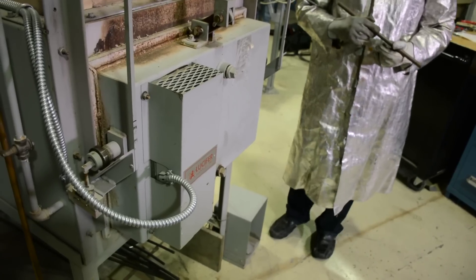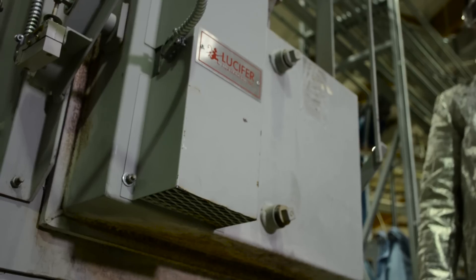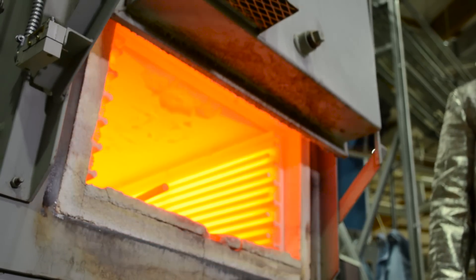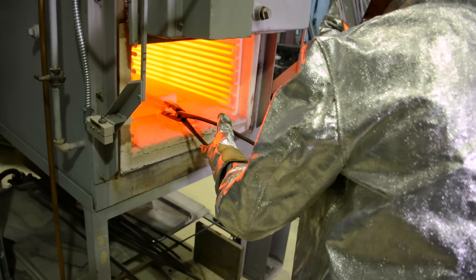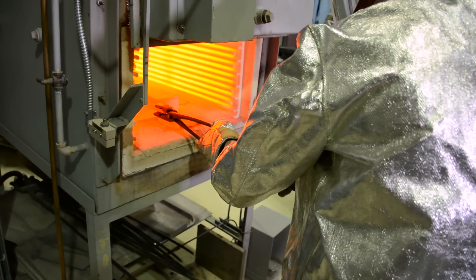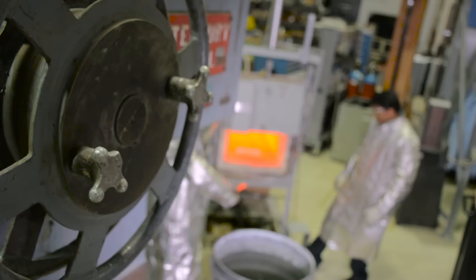What we do here is we heat treat it at between 1300 degrees Fahrenheit to 1475 degrees Fahrenheit in order to rearrange the atoms uniformly in the matrix. And then we heat it for specific amounts of time to study how the atoms rearrange themselves. Then you essentially anneal it again at a fairly lower temperature, like 900 degrees Fahrenheit.